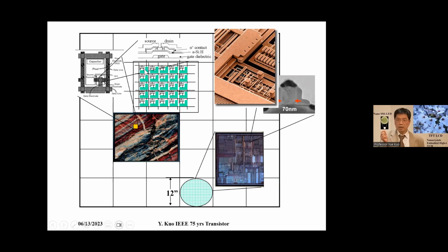While for TFT LCD, the line widths are typically bigger. For example, a few microns, 10 microns, which seems wide. However, the display size is so large that the line had to be continuous through the whole display. So it's very challenging work. Because the line width is a few tenths of the diameter of a human hair, you make it as long as tens of inches. And that's a challenge. But those interconnects had to work before the product is available.